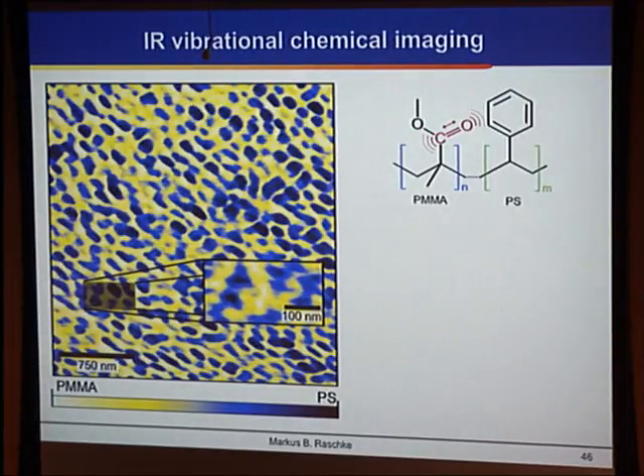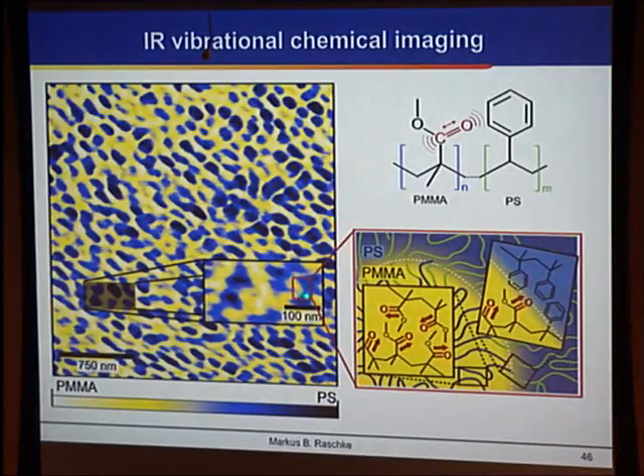So the way the experiments are typically done, we first probe a particular vibrational oscillator as a metric for the type of chemical constituents we're looking at. Then you can reconstruct a map of the distribution here of this block copolymer: where are the domains with the polymethyl methacrylate and where are the domains of the polystyrene. And then you can zoom in and really try to understand what happens at these local nano interfaces, where you have this very dense, strongly coupled and strongly dipole-interacting carbonyl functional group as it dilutes out into this polystyrene region, which has, of course, a very low carbonyl density.